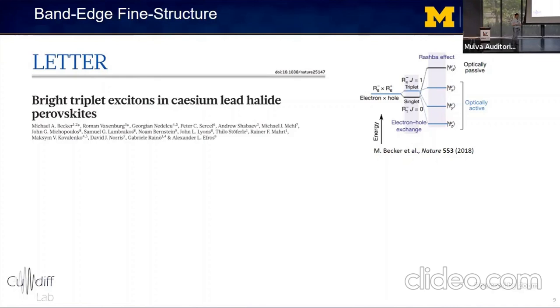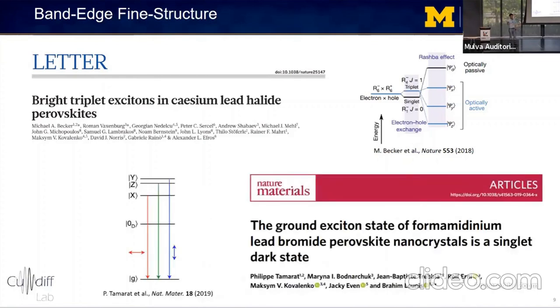But in 2019, another paper came out that studied these perovskite nanocrystals using magneto-PL spectroscopy, which presented pretty convincing evidence that the lowest exciton state in their system was actually dark. And this caused quite a controversy in the community and was one of the motivations for us to apply 2D spectroscopy to study the exciton fine structure in these nanocrystals.